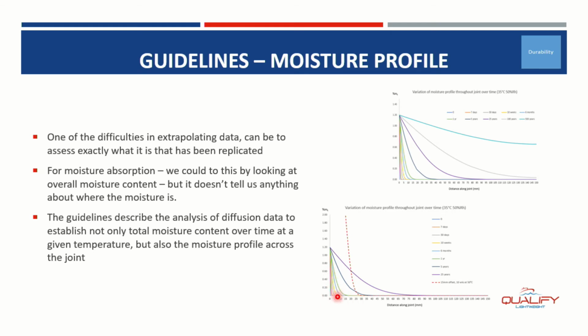Say, for example, here we've got 10 weeks of testing. We've shifted it by taking 10% of the joint away, assuming that that joint's already degraded. As you can see here, we can quite nicely replicate in 10 weeks at accelerated temperature what would happen in normal service conditions for 5 years, which gives us a nice interval between inspections.